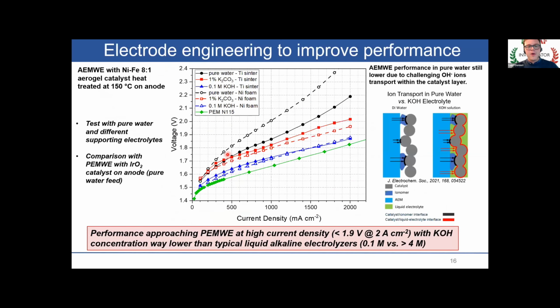Finally, comparing our results with those of a state-of-the-art proton exchange membrane electrolyzer that uses iridium oxide as the catalyst at the anode, we showed that we were able to get very close when we operated the electrolyzer with a low concentration of KOH solution of 0.1 molar, which is way lower than the more than 4 molar used in the liquid alkaline electrolyzers. However, the performance in pure water is still lower and requires more investigation due to the challenges in the transport of the OH ions within the catalyst layer, which in presence of DI water only relies on the interface between the catalyst and ionomer.